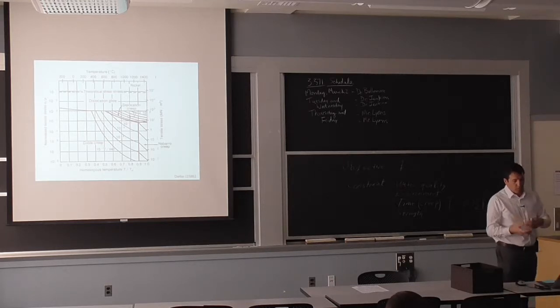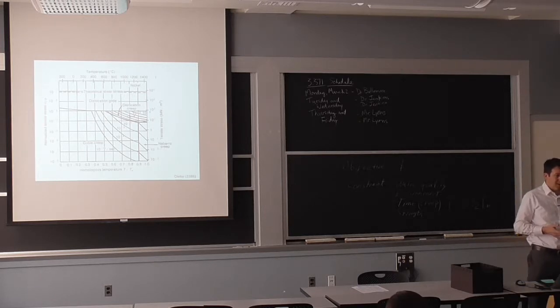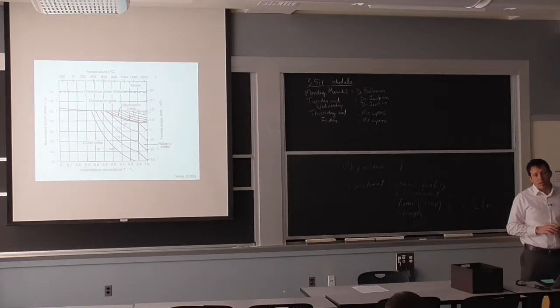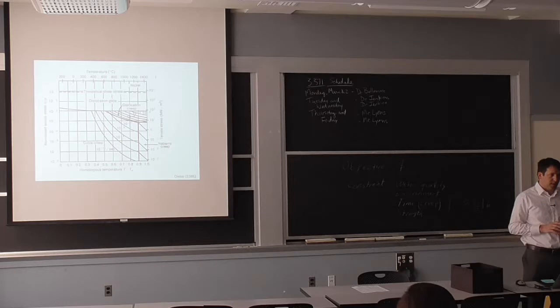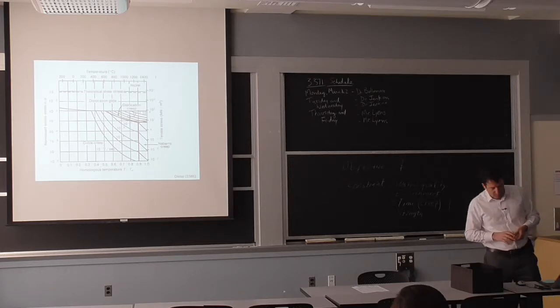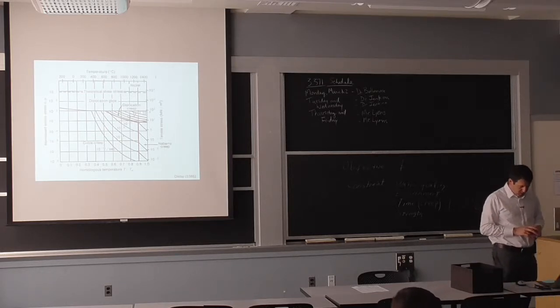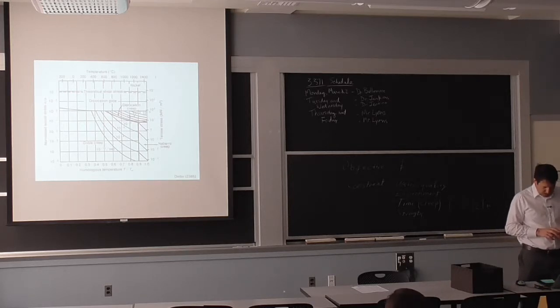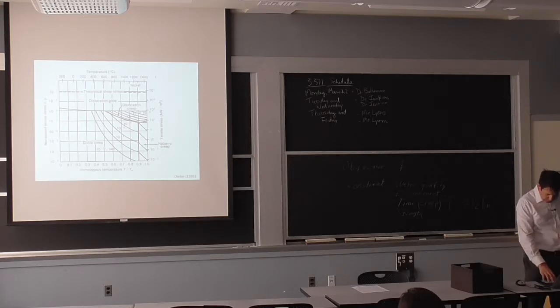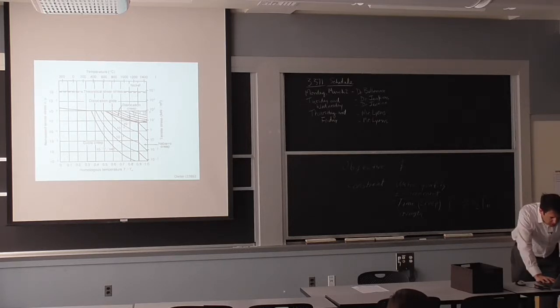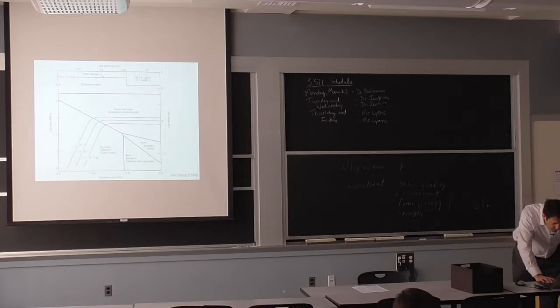And therefore you can get more diffusion, you can get grain boundary sliding in very specific situations, and therefore if you have a single grain, now you're forcing all that creep behavior to take place within the crystal, and that's a slower process. So very high temperature application, turbine blades, which we'll discuss later. The most critical application, you end up with single crystals for that reason.